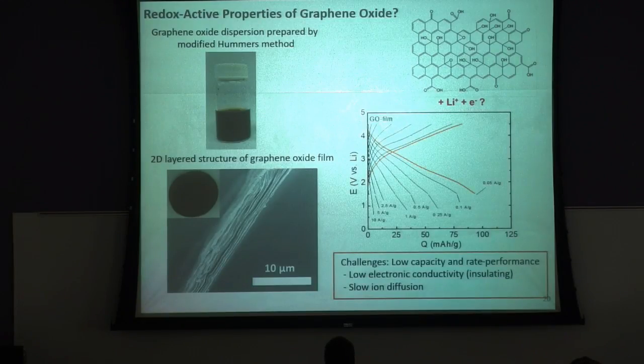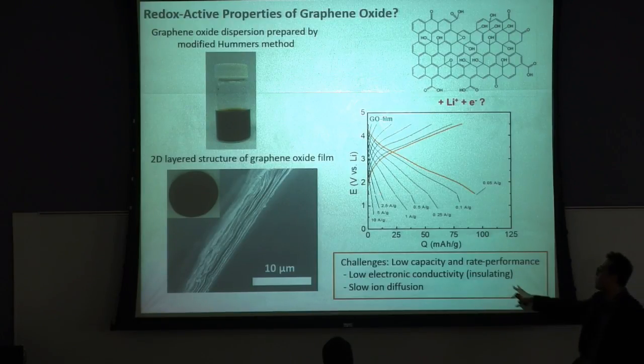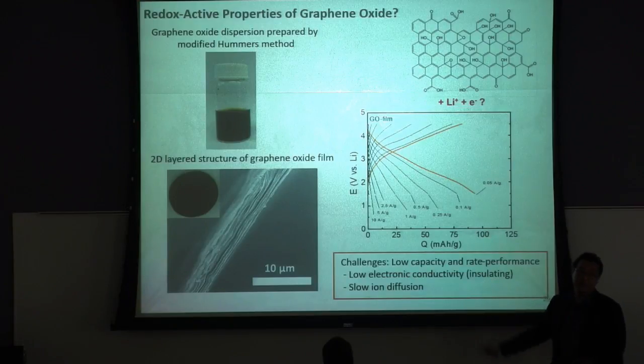So then we measured this graphene oxide film in the lithium cell. As you can see, there is some capacity, around 90 milliampere hours per gram. But the capacity is not so high, and also the rate performance is very poor. As you can see, if we increase the current density, the capacity quickly decreases, right? So I believe this kind of poor performance is because of the low electronic conductivity of the graphene oxide. Graphene oxide is almost insulating, right?